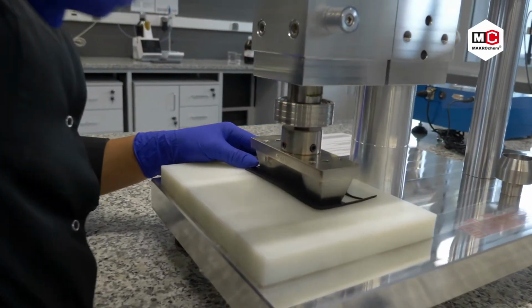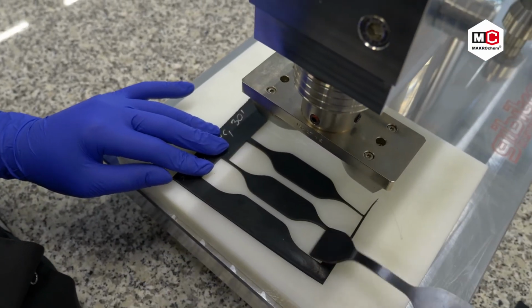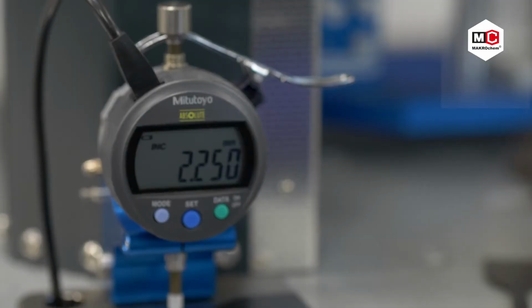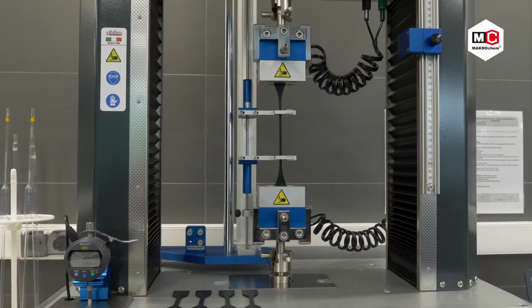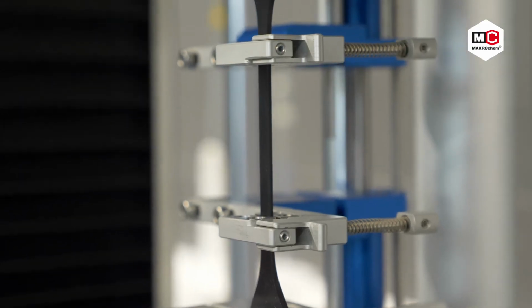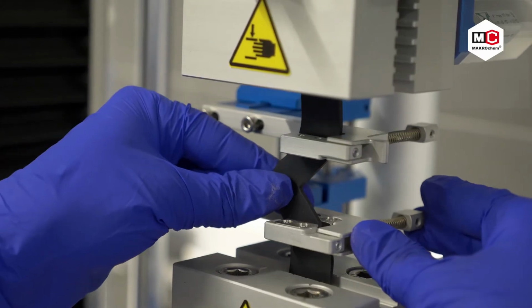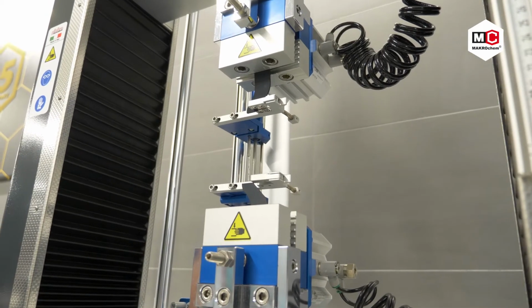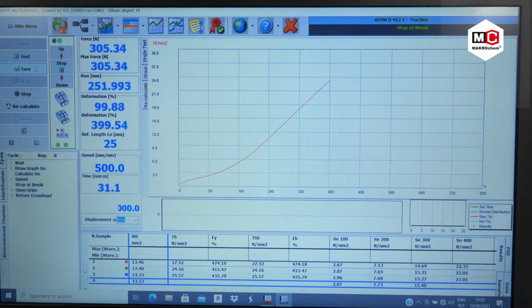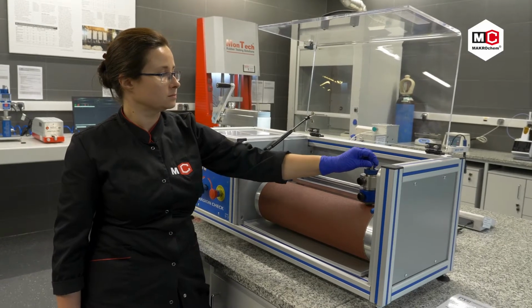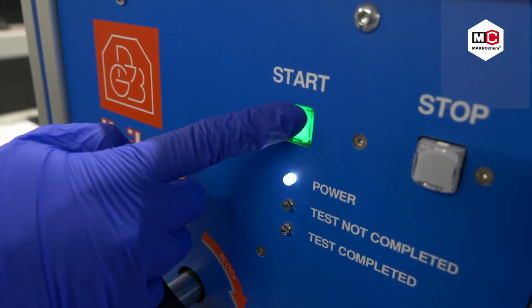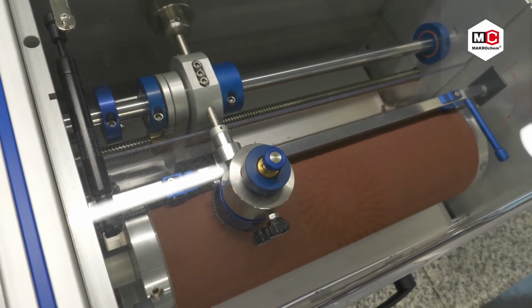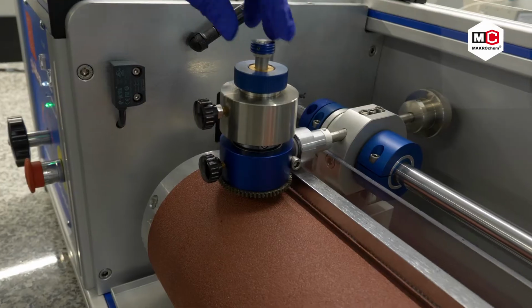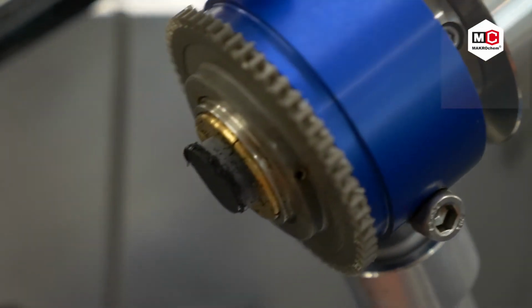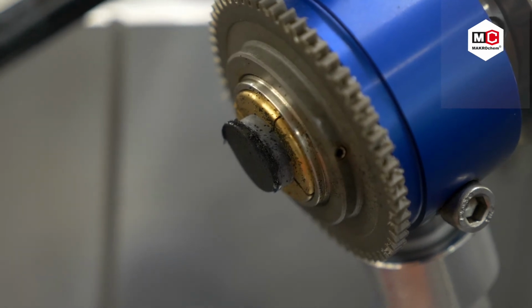It defines it and allows to evaluate the correctness of production processes. Secondly, using a tensile testing machine, we estimate durability. Tensile strength at break, strain at 100%, 200% and 300% elongation, elongation at break and tear resistance. Durability parameters indicate the quality of the compound and are used in further engineering calculations. An important characteristic of rubber is its abrasion resistance. In our R&D center, we use a rotating drum and measure the loss of volume of the sample subject to an abradant on specified distance, time and pressure.